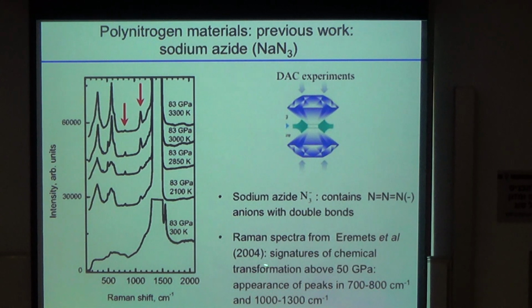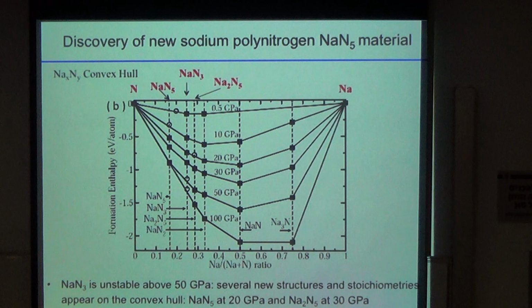Because there was an experiment by Eremets and others, they wanted to find a single bonded form of nitrogen, but they tried different things. They tried pure nitrogen compression, which needed extremely large pressures. They tried to use sodium azide, containing N3 minus, this azide group that contains double bonded forms of nitrogen. And they thought that if they heat and compress this, they might see the single bonded form of nitrogen. So upon the compression and heating of this compound, at around 50 GPa, they saw the appearance of two peaks in the Raman spectrum. There was no crystal structure determined. This spectrum wasn't explained. They put forward some hypotheses about what it might be, but there was no explanation. So when we started our research, we completed this in a systematic fashion. We did searches at different pressures, almost at ambient conditions, 10 GPa, 20 GPa,